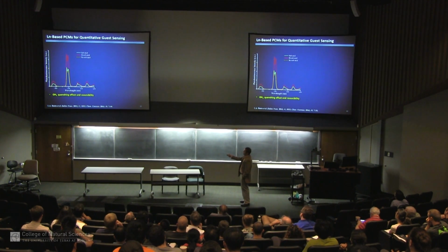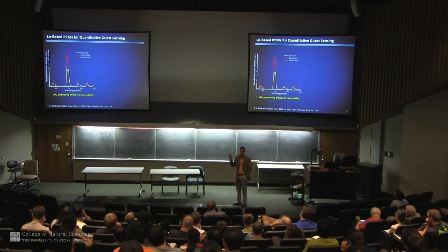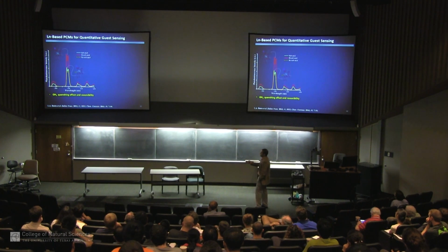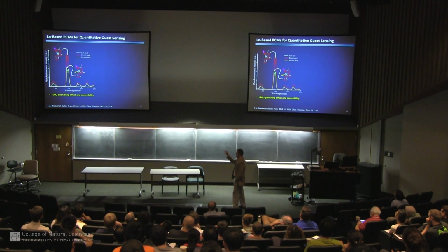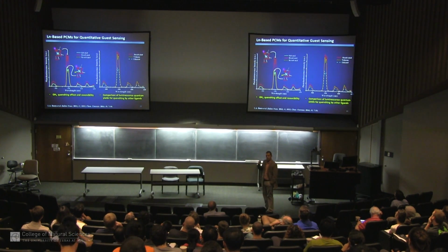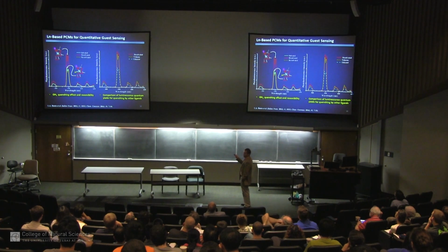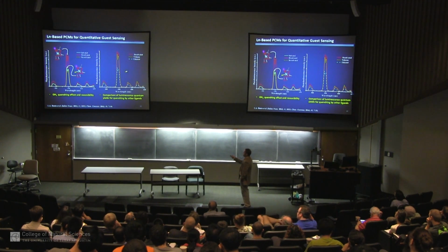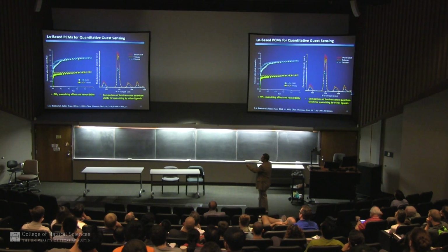It decays by luminescence. Now, if you have water close to the lanthanide, or some other groups, certain bonds, like OH bonds in water, quench luminescence, so they're bad. If they're close to the excited lanthanide, you get non-radiative quenching. And so we know for a fact, if we're in this state, the luminescence is low, and then it doubles when you remove this water. Well, you might say that's okay, we've got a handle to describe what's going on in the material, but it's more useful than that, because we can start putting other solvents back inside the pores and seeing how they affect the luminescence intensity. So you see something like ethanol, which can get close to that lanthanide and bind to it and bring an OH bond close by, also quenches, but something like toluene doesn't quench at all because it just sits in the cavity. We always check to make sure that the solvents are inside the pores.